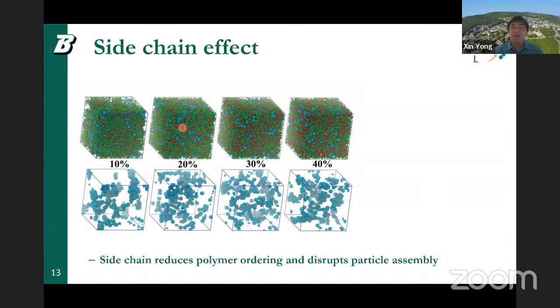So here we are adding soft side chains to the primary chain, to the backbone, from a distribution of lengths and randomly along the backbone. And we vary their concentration in terms of how many side chains they have along the backbone, and that's represented by this percentage. And what we see here is that the general trend is very clear: the introduction of side chains reduces polymer ordering, because now they have to overcome a much higher entropic effect to develop the nematic order. So overall it disrupts the polymer ordering and also reduces the particle assembly structure.